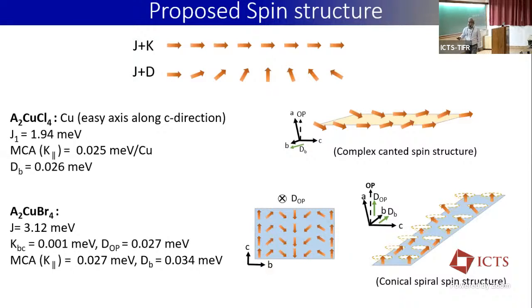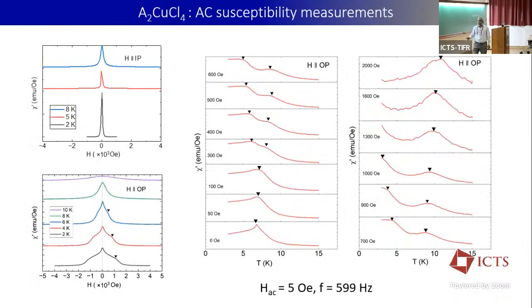But on top of that, it is not only out of plane, you have an in plane component also, which is kind of comparable. So because of this, you will have not only a spiral, you have a conical spiral spin structure. To look more into it, we did the AC susceptibility measurement. You see, when you apply a field in the in plane direction, it shows only one peak, a characteristic transition temperature. But when you do the AC susceptibility with the field out of plane, you see a small bump coming here. And if you look at the susceptibility versus temperature, there was only one peak.